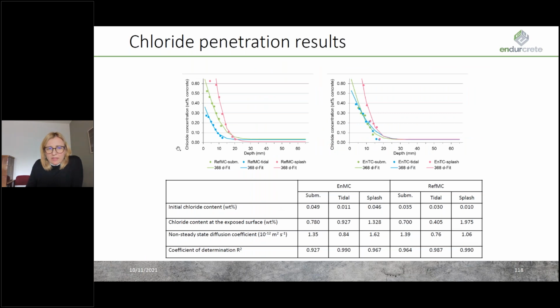You can see some of the results of the chloride penetration tests. Very briefly, the chloride surface content is highest at the splash zones, as you can see in both the EnDurCrete concrete and the reference marine concrete used with the reference cement. Generally, we can see very low diffusion coefficients and very similar behavior from both EnDurCrete and the reference concrete.